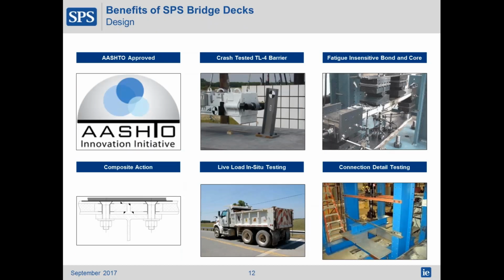SPS has undergone extensive testing to characterize its performance over the last 20 years. In particular for bridge decks, the crash performance, fatigue, and dynamic properties are all important for designers. We've found that through testing, SPS is able to achieve at least a TL4 performance level. The polyurethane as well as the bond to the steel plates were found to be fatigue insensitive, and any fatigue is governed by the parent plate and connection details, again typical to any steel bridge design. We've also done live load testing on the bridge deck and found that the dynamic impact properties are consistent with that of AASHTO. Of course, all load reports and assessments can be made available to you.